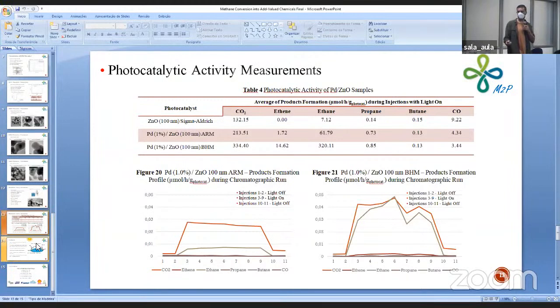At figures 20 and 21, we have the product formation profile during the injections. At injections 1 and 2, the light was off, so we have no product formation. When the light was turned on, at injections 3 to 9, the activity is higher. We have the product formation. And then when the light is turned off again, the activity drops down.